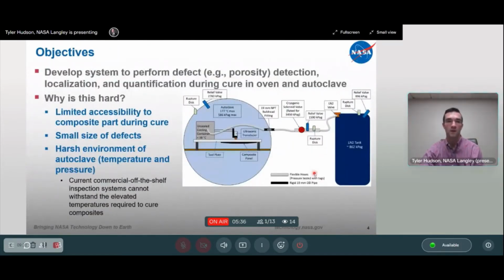So here's the objective of the system: to be able to detect, localize, and quantify defects such as porosity during the cure cycle. And this is hard primarily because of the harsh environment of cure. So this is a PowerPoint drawing of what the system looks like. You have your composite part that you're making. You're inspecting it using an ultrasound transducer, and there are electronics inside this housing. Those electronics would not operate at 350 Fahrenheit and up to 100 PSI. We cool those electronics using a liquid nitrogen cooling system.